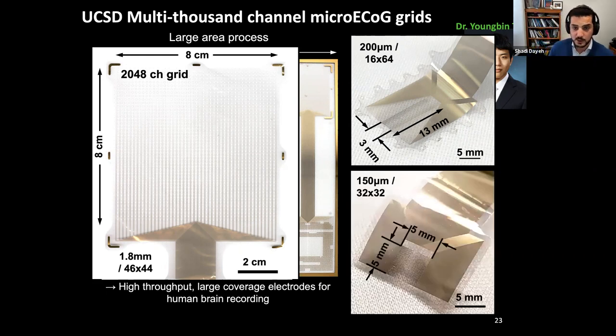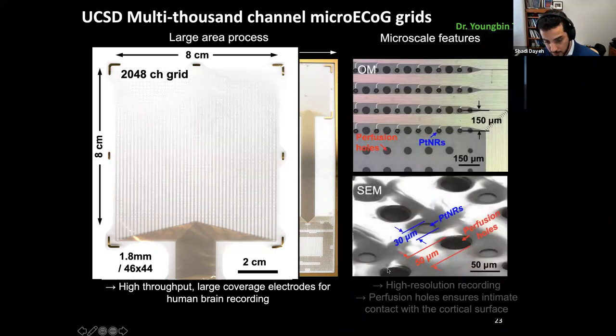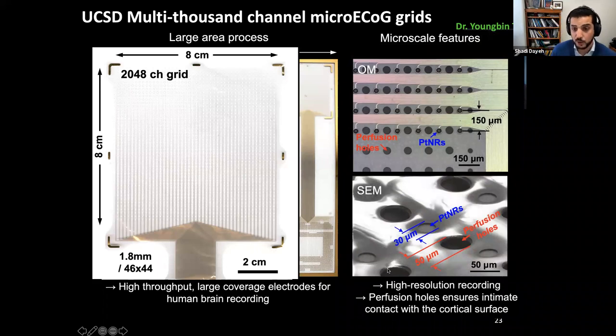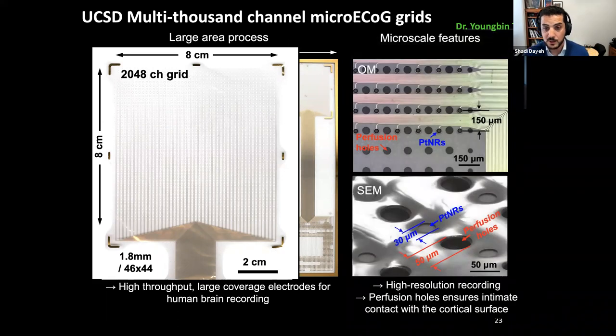Now the design is flexible so that you can bring the contacts further away from each other or closer together. So this is a high density grid that has 200 micron pitch in a 16 by 64 fashion, or 150 micron pitch. That's distributed over 4.8 millimeter by 4.8 millimeter. So this is a close-up image of the grid. Again, you can see the platinum nanorod contacts with the metal leads. And in between them, we can see the perfusion holes.